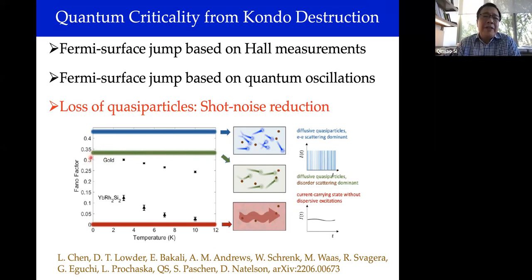measure, if you scale that by the current, by this factor called the Fano factor, in a particular regime that's of relevance to gold, it would be 1/3, and we believe that if there are well-defined quasi-particles, it would be 1/3 or even larger if it's in a different regime of the disorder versus interaction strength. While in ytterbium rhodium two silicon two, in the temperature range that has been measured, that falls in the quantum critical regime, the Fano factor is substantially smaller than the expected 1/3 or larger value. So that is, at least to me, very striking evidence for the loss of quasi-particles in the quantum critical regime.